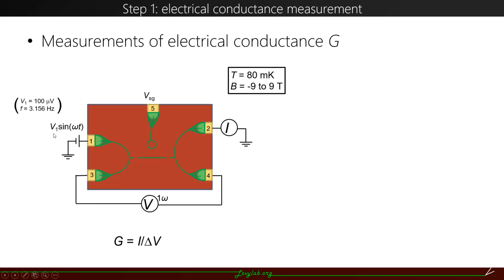Specifically, we apply a sinusoidal source voltage with an amplitude of 100 microvolt at a frequency of 3.156 Hz to terminal 1, while terminal 2, which is a drain, is grounded. Then we can measure the voltage difference between terminal 3 and 4 at the same frequency, as well as the drain current, and the electrical conductance can be obtained as the current divided by the voltage difference.